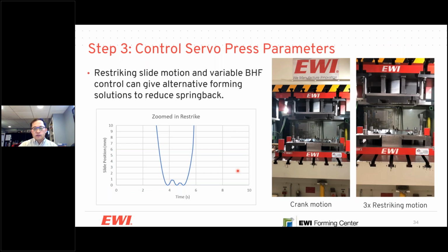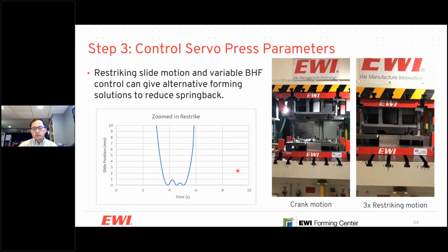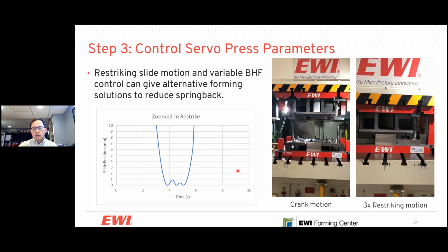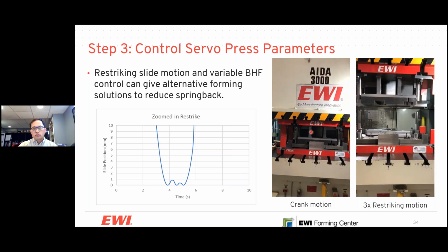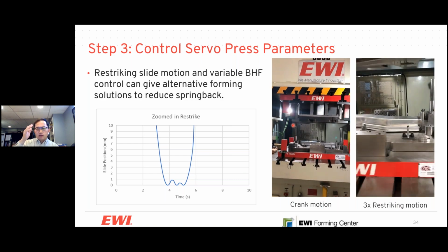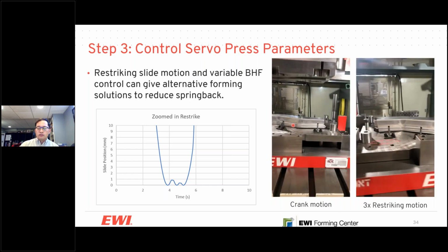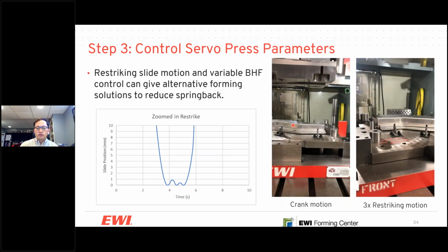In our experimental validation, this again shows 2 different press motions: one is the crank motion in the lab, the other is a restriking at the bottom dead center. People use a restriking die, another set of dies, to calibrate springback or geometry for springback issues, especially with high strength material. But this servo press allows us to restrike the part through the press motion, so that we hit the bottom dead center 3 times, offsetting only 0.8 millimeter from the blank. It does not significantly delay the production rate, but is actually more effective for springback control.